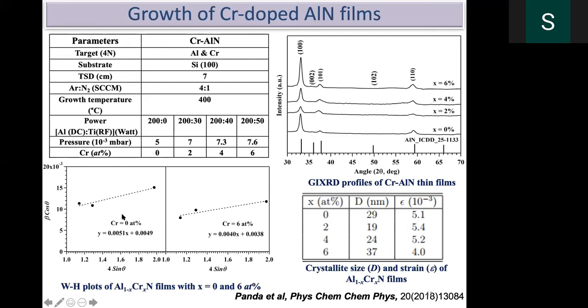And this is a plot to understand the residual stress of the system. When you increase the percentage of chromium, how does the growth of the thin film vary with stress? Here it's 0 atomic percent and 6 atomic percent, but there is no big difference in the slope. So it's almost the same.